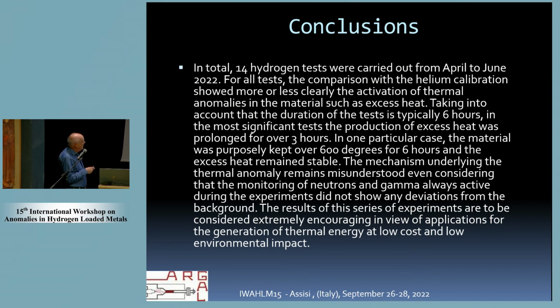The mechanism underlying the thermal anomaly remains misunderstood, even considering that the monitoring of neutrons and gamma, always active during the experiments, did not show any deviation from the background. The results of this series of experiments are to be considered extremely encouraging in view of application for the generation of thermal energy at low cost and low environment impact.